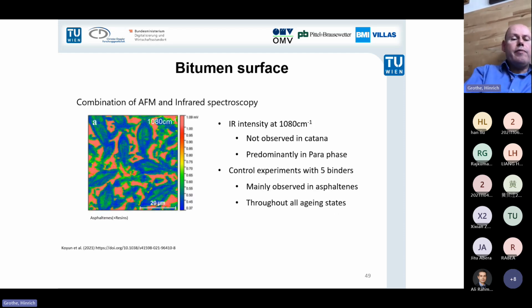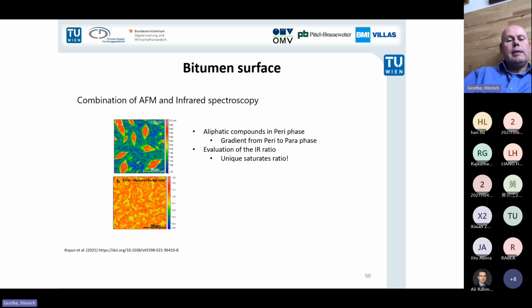And then we were also correlating the AFM with the infrared. That's its own kind of spectroscopy where you actually are using the AFM as a detector for the infrared absorption. And this here is recorded at a band of 1080 wave numbers, and you can really see the heterogeneity of that surface. And this is an aromatic signal, and you can see that the aromats are not observed in the katana, but predominantly seen in the paraphase. And you can also do that, of course, with other bands, and then understand the distribution of different compounds in that surface, and really learn how different chemical compounds are situated in the bitumen surface.